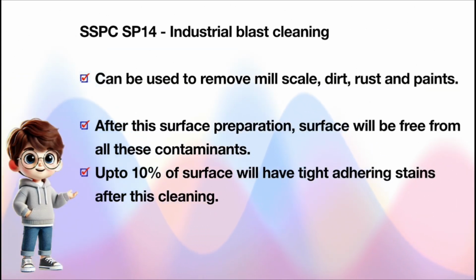Next one, SSPC SP14, industrial blast cleaning. Before doing this surface preparation, the surface may have oil, grease, dirt, dust, mill scale, rust, coatings, oxides and corrosion. After this, the surface is free from all these contaminants, with traces of tightly adhering mill scale, rust or previous paints; it will allow only 10% of the surface to have stains.